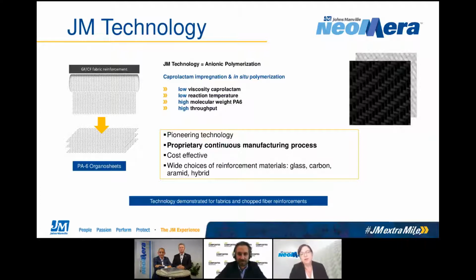So the JM technology is innovative, and it's innovative in the sense that we are creating organosheets not by using conventional melt impregnation, but by forming the polymer in situ, in place in the reinforcement. So the schematic here to your left shows a roll of glass fiber fabric that we take as a raw material, and then we impregnate with a low viscosity caprolactam, which is the monomer for polyamide 6, the precursor for polyamide 6. And we polymerize the caprolactam anionic in situ in the fabric.